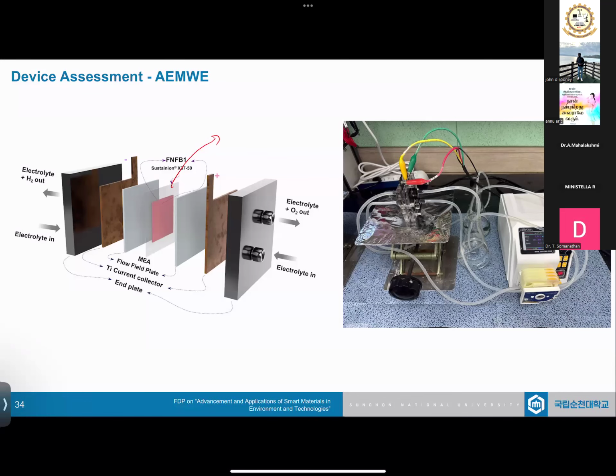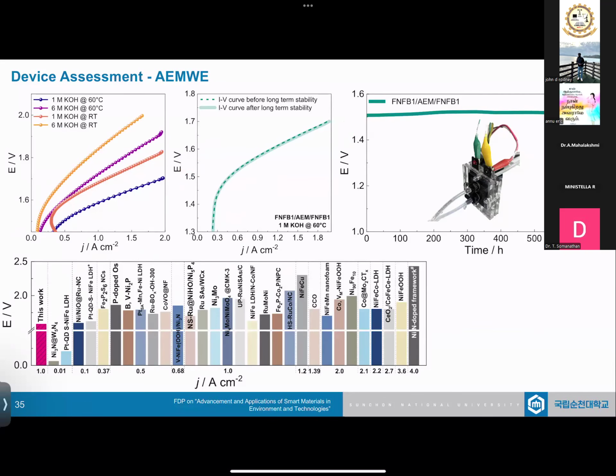So what did we do? We did the AEM testing, for different electrolytes, different temperatures and everything. And we did a long-term study of 700 hours, which is still not that long, but okay. 700 hours at 500 milliamps. This is also something I will urge: most of the people working on water splitting are reporting papers with 10 milliamps or 100 milliamps long term, which is completely wrong.